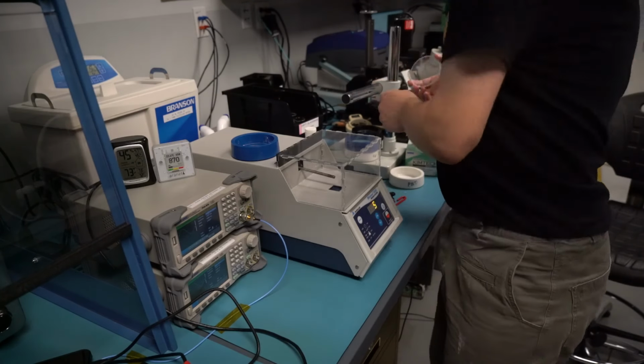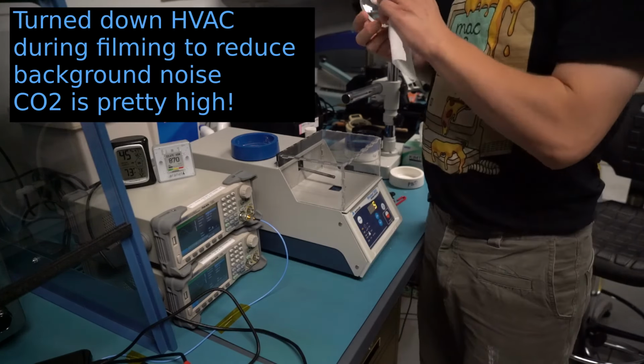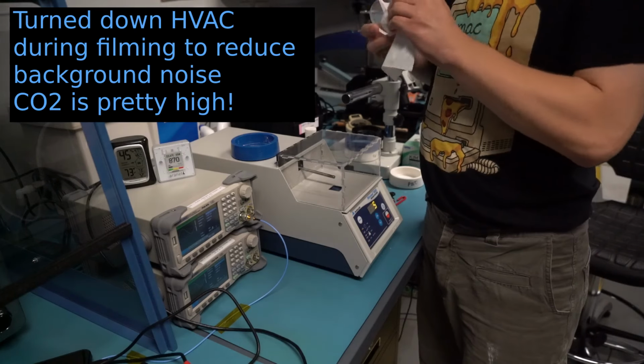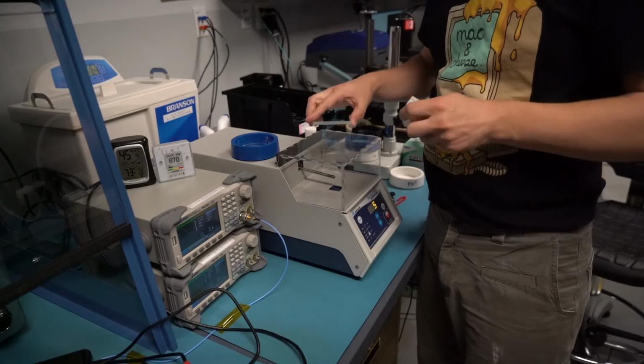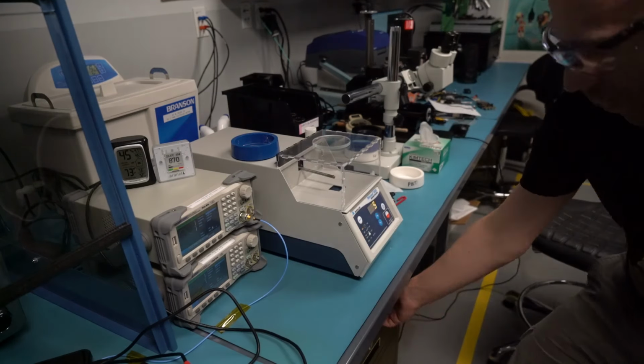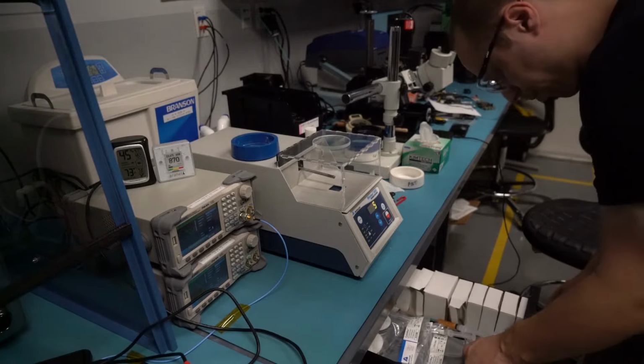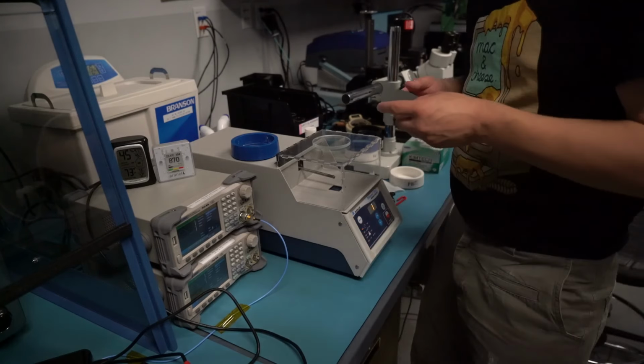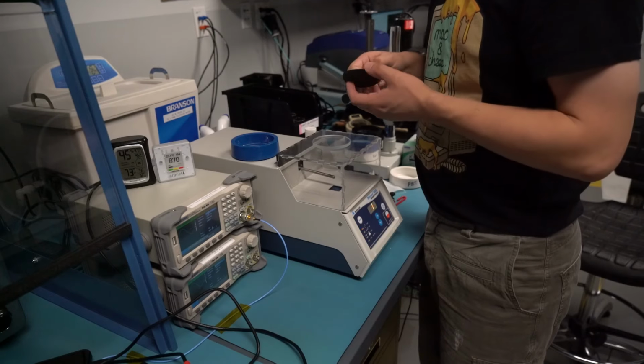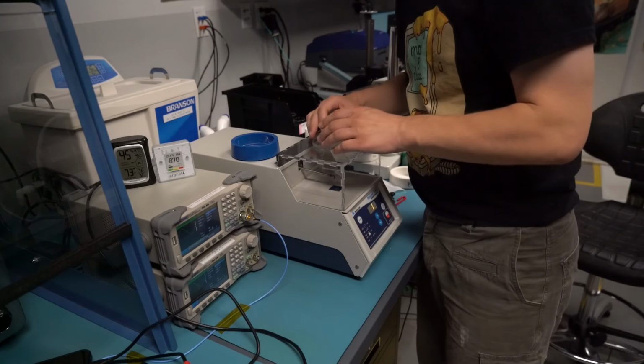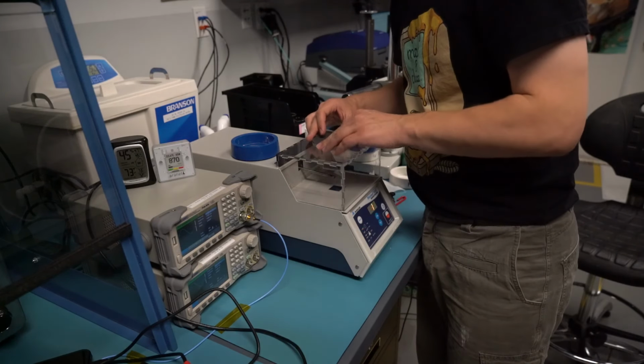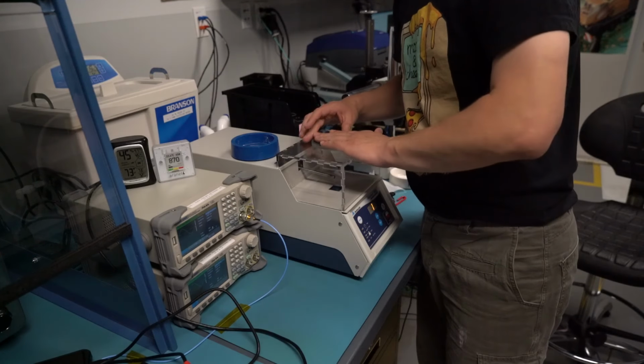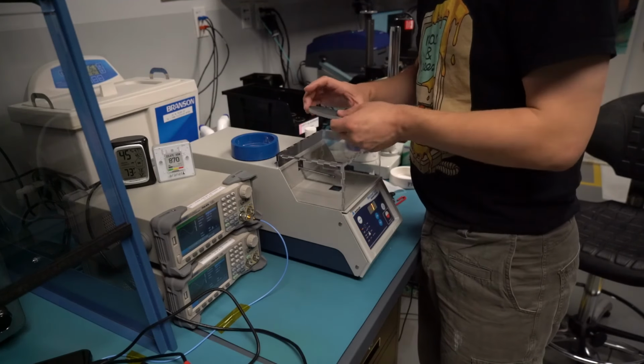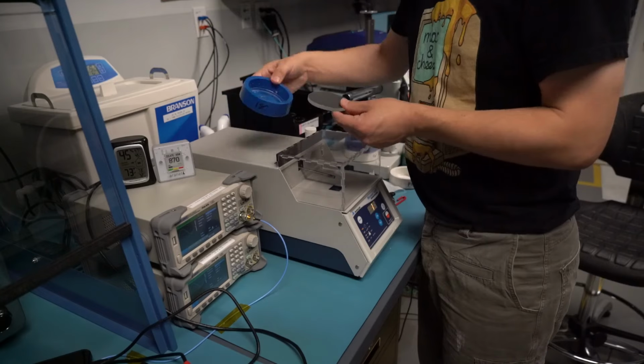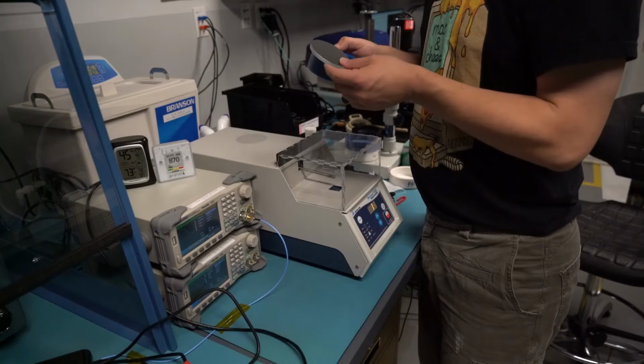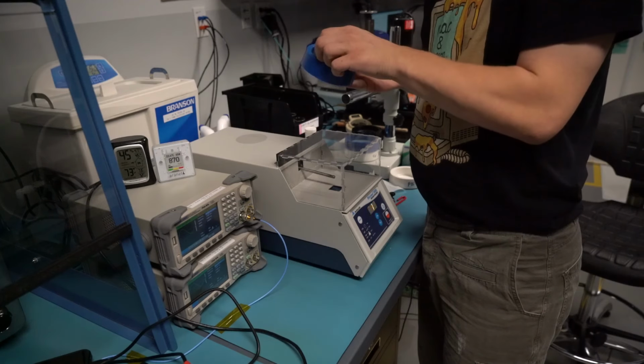So while we're waiting for the resin to cure, I'm going to prepare the polisher with a P180 silicon carbide abrasive sheet. The goal here is just going to be to rough thin the sample, remove any of the meniscus on the edge of the sample, and get the surface nice and flat so that when we're doing thickness measurements later on, we've got a baseline to measure against.